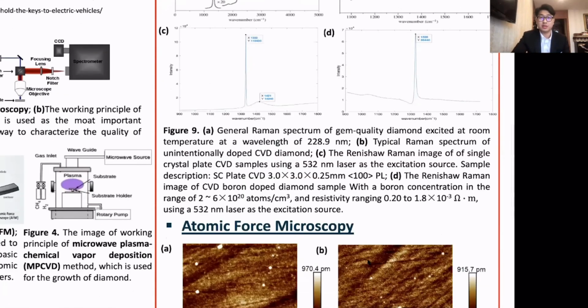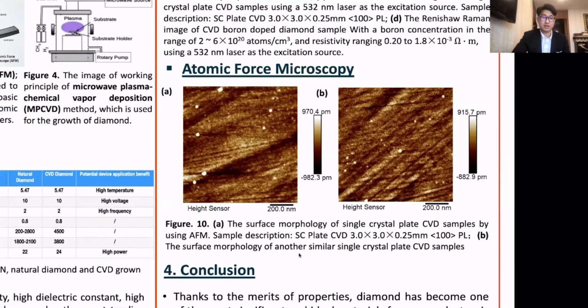Then let's move on to the atomic force microscope results. Figure 10 shows the surface morphology of single crystal plate samples by using atomic force microscope. And we can see that the surface roughness is very small, which means the surface is very smooth, and it is a high quality sample, which is different to the polycrystalline diamond sample, which may have the higher roughness and some gaps in the surface.